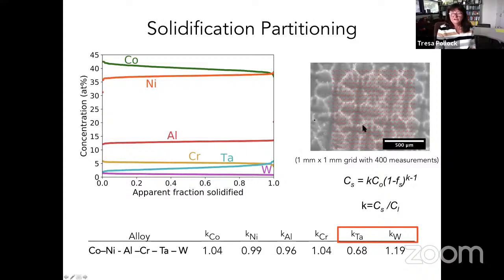Now, when one solidifies materials at moderate gradients and velocities, you always have a dendritic structure. And the contrast that you see here is due to segregation during solidification. So if you go to the electron microprobe and lay down a fine grid of points and measure composition and plot those compositions based on low to high cobalt, because that's what one would expect for a solidification path, then you can fit to these curves a Scheil analysis for solidification.